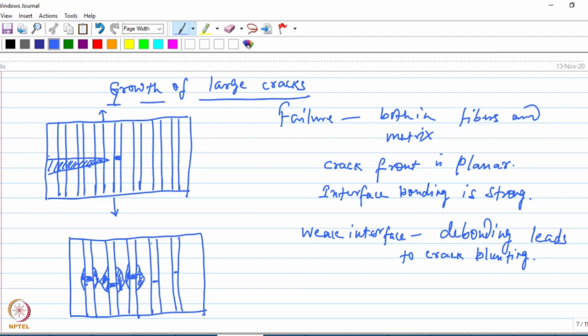Something like that, right? So there is a debonding at the interface, which leads to crack relaxation, or crack blunting. And in this case, you can see that the matrix crack and the crack in the fiber are not really in the same plane. So therefore, here the fracture is non-planar, unlike the previous case where it was a planar fracture or planar crack front, right? But in this case, the matrix crack and the fiber crack are not necessarily in the same plane, and therefore it is a non-planar type of fracture.